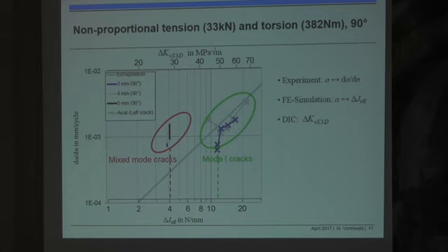However, if we now go to the variable mode mixity, mixed mode cases, we arrive at 4 Newton per millimeter at a crack growth rate of 10 to the power minus 3, so we are far away from what I would have expected. So the J effective at the moment is out of the race. Remember this number of 40 megapascal square root meter from the FE evaluation.